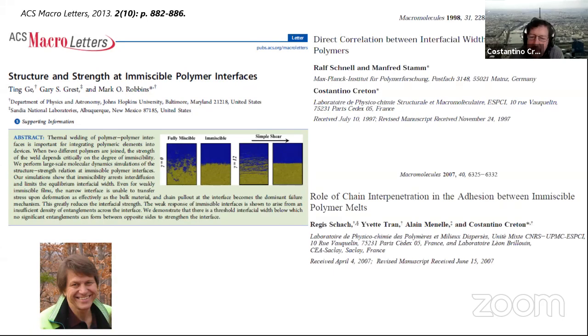Another paper that concerns interfaces that we worked on was in 2007. Then it was polymer melts. In this case, we were looking really at polymeric fluids, and how very high molecular weight polymeric fluids that look more like viscoelastic solids could stick to each other, again, depending on how they interpenetrate. And in this experiment, there was very much a coupling between molecular effects and bulk effects. It was impossible to really localize the problem.